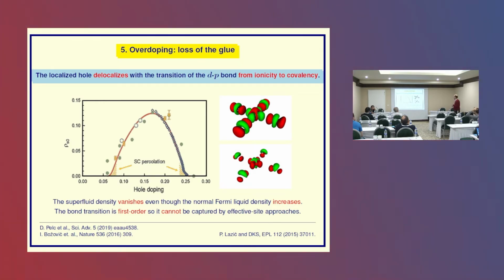Okay, and here, again from this old calculation, you can see the difference between the ionic bonding and the covalent bonding. In the ionic bonding, you can see that the copper has pushed, red is positive charge, the copper has pushed positive charge onto the oxygen, but at the price of having negative charge here. So you have a Coulomb gradient here, which prevents the hole on the oxygen from hopping back onto the copper. Okay, that's the nature of the ionic bond.